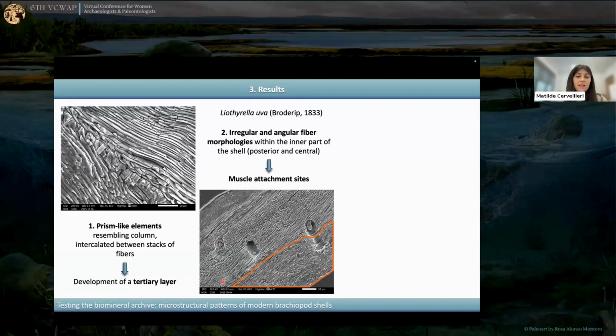Another interesting feature is that we have this region in orange in the inner part of the shell section, with irregular and angular fiber morphologies. This is related to muscle attachment sites, and it is particularly important to have found this feature in modern brachiopods, since when we are dealing with fossils and doing diagenetic screening, if we normally see something really altered as this microstructure, we end up thinking that some diagenetic processes were acting, whereas if we can locate this region in the innermost part of the shell, we might also end up considering that it might be related